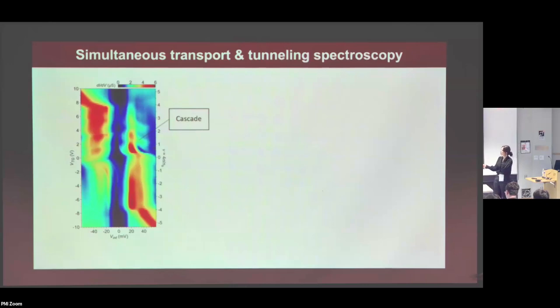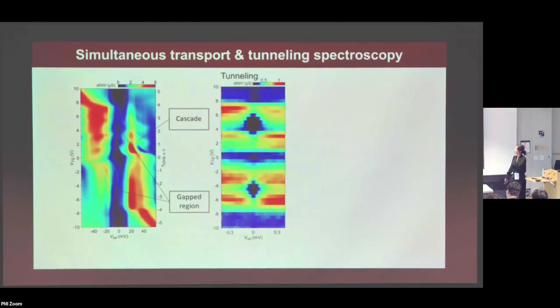But in addition to that, if you go into a slightly smaller energy scale, you have these very low tunneling conductance regions, which might be gapped regions. So we also want to zoom in on what's going on there. You can zoom into a very, very small energy scale, which is plus minus 0.3 milli-electron volt in the same axis. And you can see that there are actually these dips in tunneling conductance. So there might also be a gap. Then what kind of gaps are there?